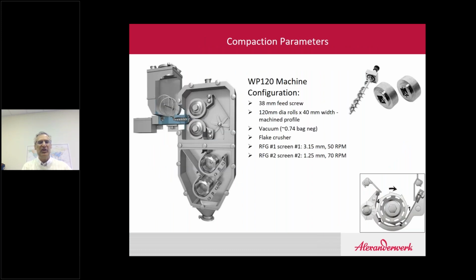The material was put into the WP120 from Alexanderwerk, and the way the machine was configured is we used a 38mm diameter feed screw. We used 120mm diameter rolls, which is what the WP120 actually stands for, and the rolls were 40mm in width. Vacuum that we ran was about 0.74 bar negative. We used our flake crusher running at about 50 RPM, and then the 2 RFGs below. The first RFG had a screen of 3.15 millimeters. We ran it at 50 RPM, and the final RFG had a screen of 1.25 millimeters running at 70 RPM.